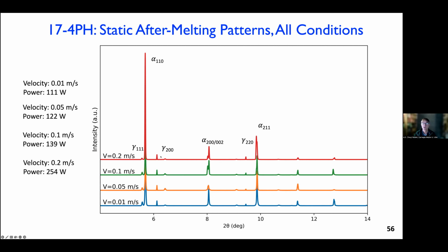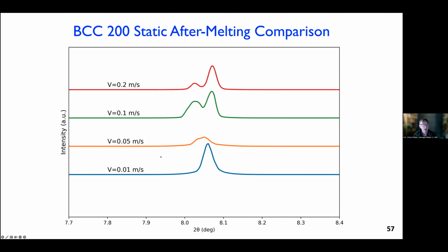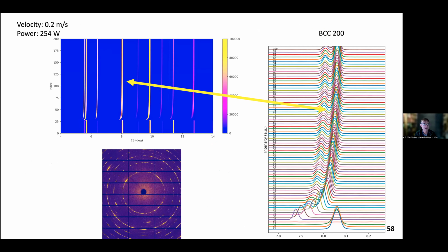And you can have the FCC phase as well, and typically you see some of that, I guess, fairly consistently. But what was interesting in this was to look in more detail at this 200 peak and realize that the faster that we were going, the more obviously it was splitting into a main peak and a subsidiary peak. And then to further elaborate, this is the highest cooling rate. So you see the little movie of the diffraction patterns. And what you can see is the time dependence on that peak. And it's pretty clear that it's splitting very early on.